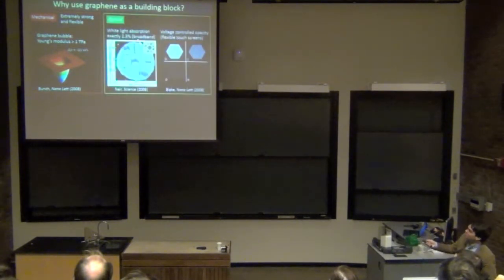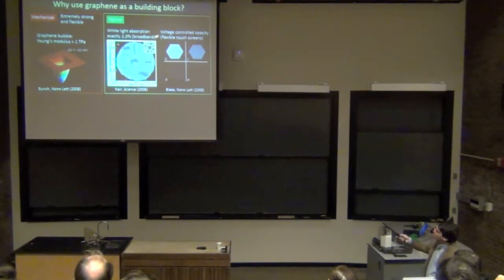For example, it's extremely strong and flexible. If you put it over a hole and put a huge pressure across it, you can measure a Young's modulus of something greater than terapascal, which is better than a lot of ceramics. It has really interesting optical properties as well. For example, it absorbs in the broadband exactly 2.3% per layer